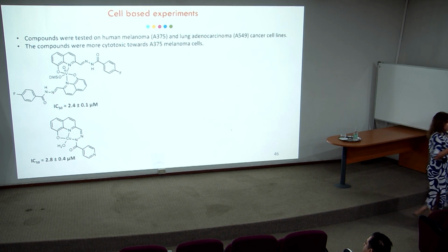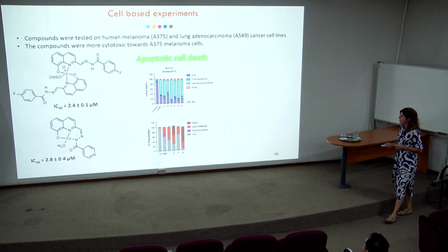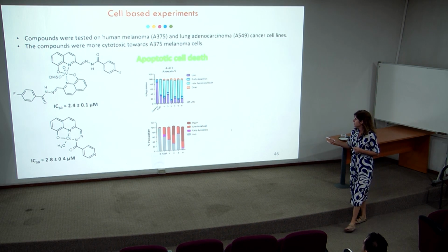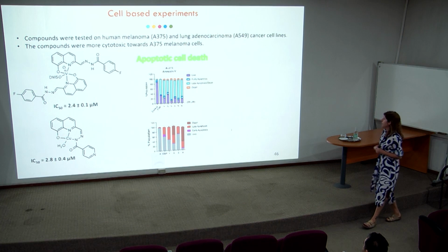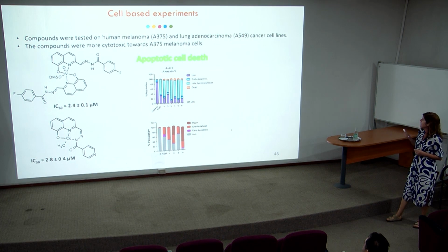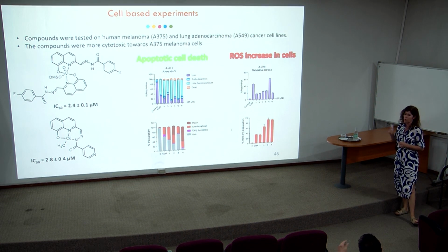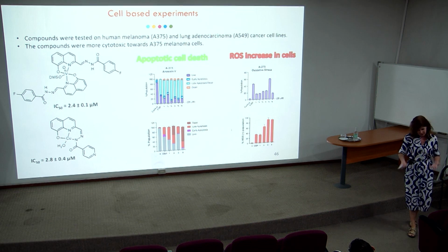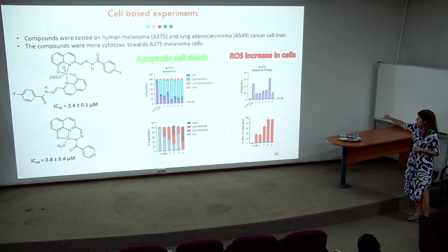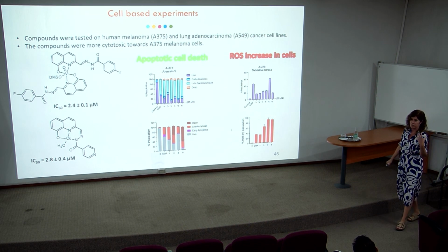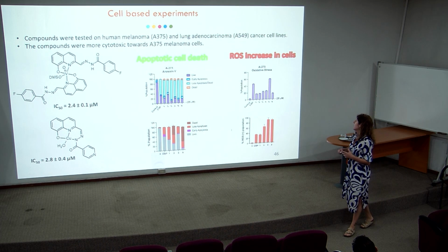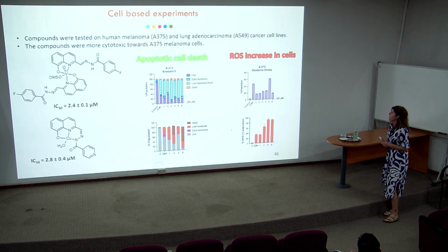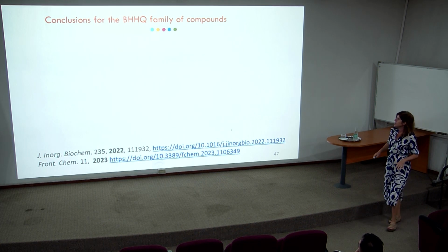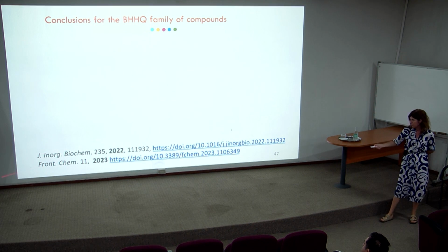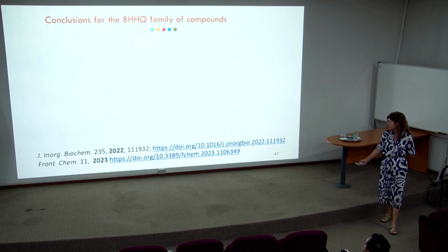So low IC50 values for these compounds in melanoma cell lines, and we studied the mechanisms of cell death. We could confirm that apoptosis, particularly late apoptosis, was the mechanism of cell death for these compounds, both for the copper and the vanadium complexes. And we confirmed the involvement of reactive oxygen species also in cell studies, particularly for copper, in which a very high increase in the ROS population was observed upon treatment of the melanoma cells with these compounds. So just a few conclusions from this family of compounds. We published the vanadium and the copper systems in these two publications in 22 and 23.